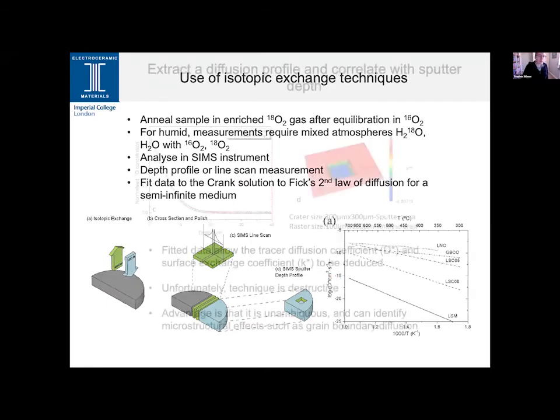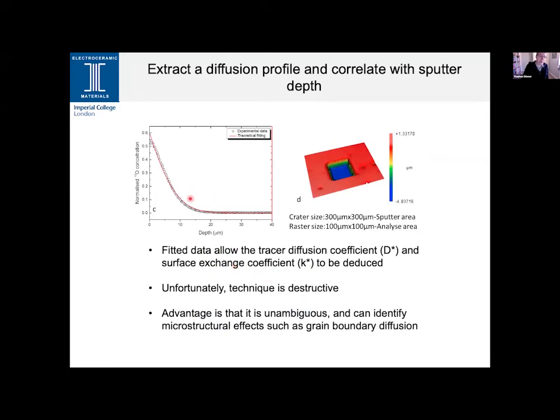So the typical diffusion profile that you would extract from this type of measurement would be our normalized concentration of our isotope against our depth. And this is a nice diffusion profile from a standard ceramic. And from that, we can then also, in a separate experiment, determine the depth of the crater and correlate that to the sputtering depth. That allows us to extract our diffusion coefficients. It is destructive, but it is unambiguous in that it identifies the tracer species, but can also extract microstructural effects if you're fortunate with things like grain boundary diffusion.